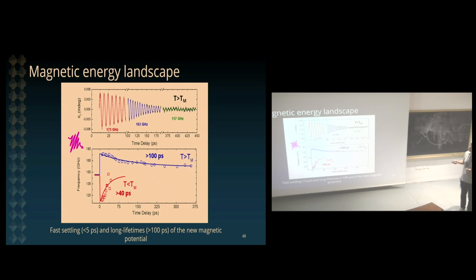In order to do so, we just let the system ring down and we wait. We probe longer and longer time delays. At early time scales, we see a frequency of the oscillations that is fast, and then you see gradually that the frequency of the oscillation decays back to the equilibrium value dictated by the curvature of the magnetic potential. If you want, you can take a Fourier transform of this data at different time windows, and you see that gradually your frequency recovers back to the equilibrium frequency, and this is shown here. So it takes hundreds of picoseconds for the magnetic energy landscape to go back to equilibrium. However, it only takes a few picoseconds for the magnetic energy landscape to change.